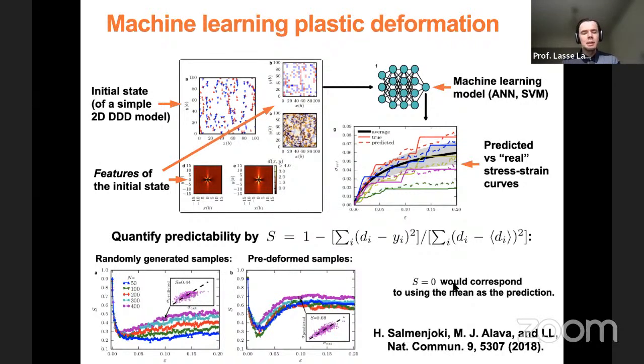Okay, so then you can just look at this prediction score S as a function of strain of your simulation. So you see that first of all, for very small strains, you get very good predictions, which is maybe expected, because if you start from some configuration, you only move some dislocations a little bit, and you kind of know based on the initial configuration roughly what it will do.